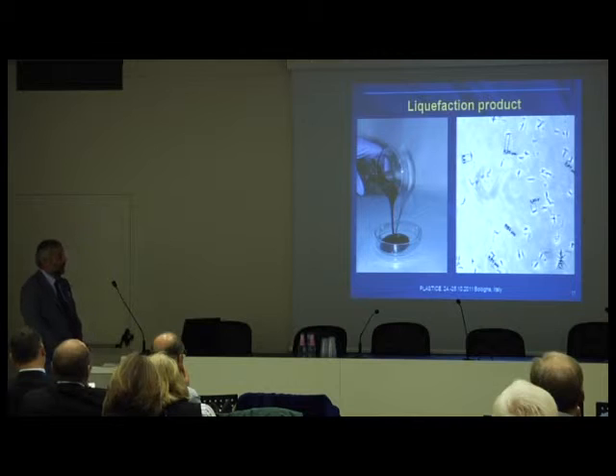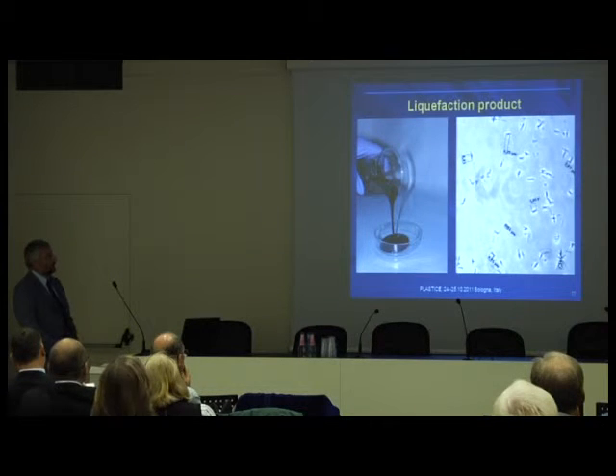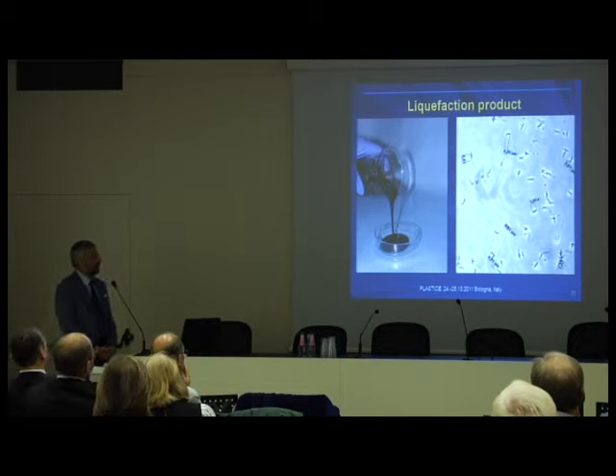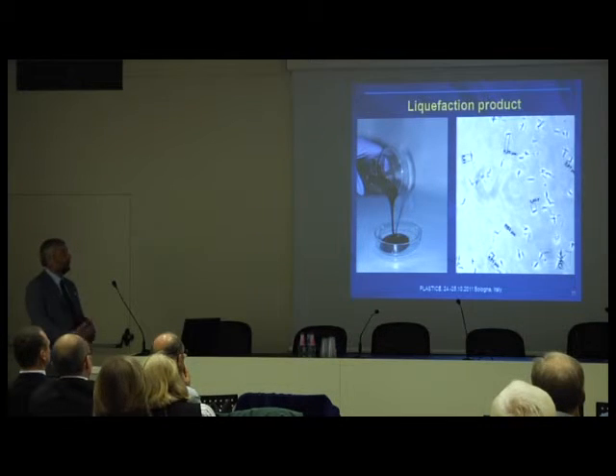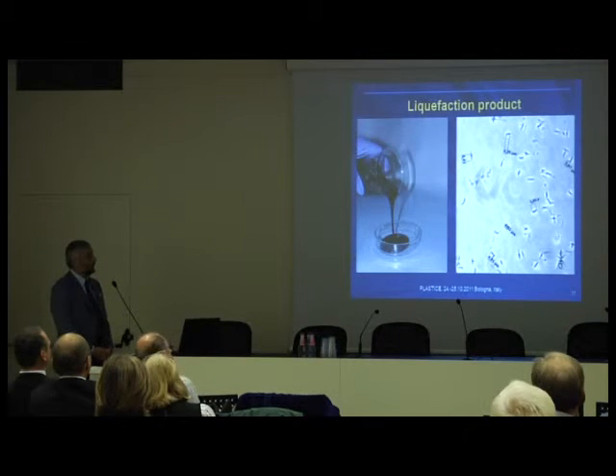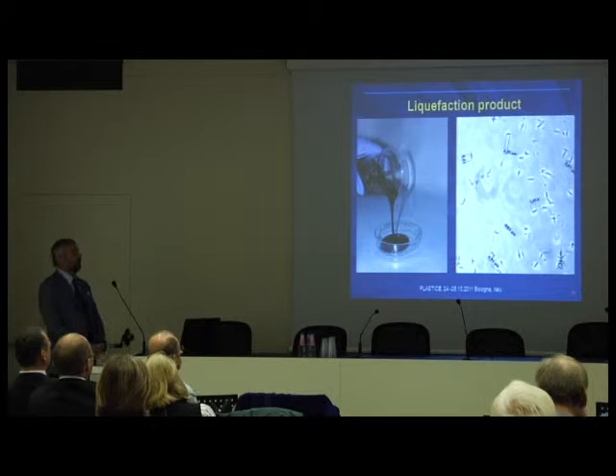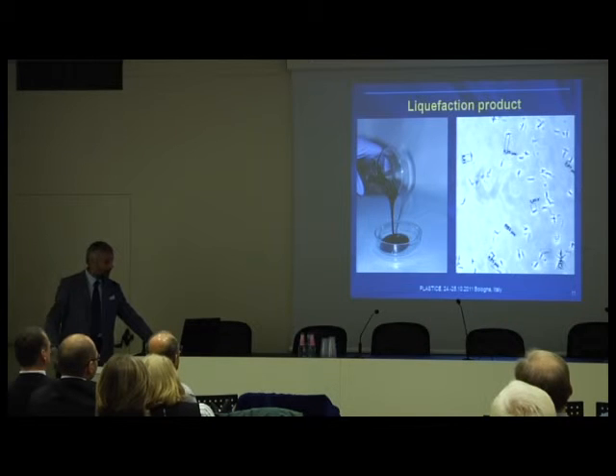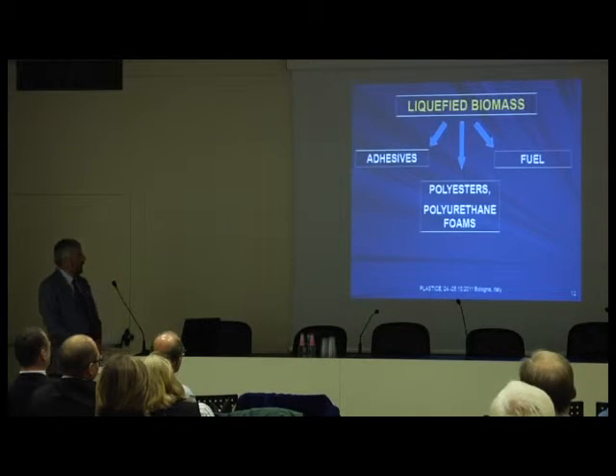The particles which are left in the liquefied product are mostly crystalline cellulose, because it is so difficult to liquefy it because of this crystal structure. If we want to get rid of also these small particles, then the reaction would take a little longer. But if the further utilization of the product is not so demanding, then we can leave it as it is.